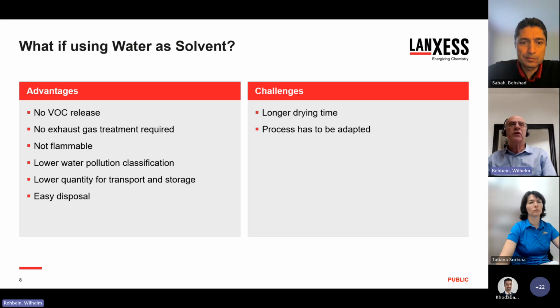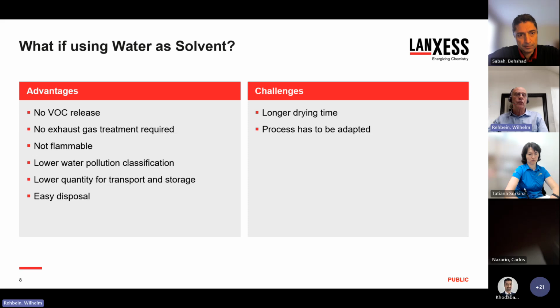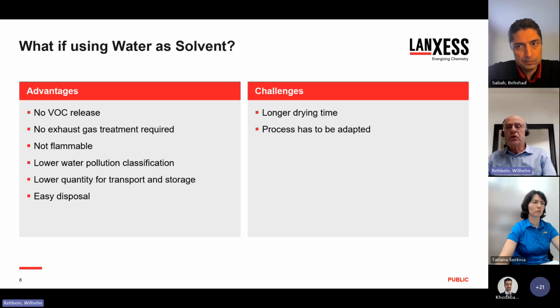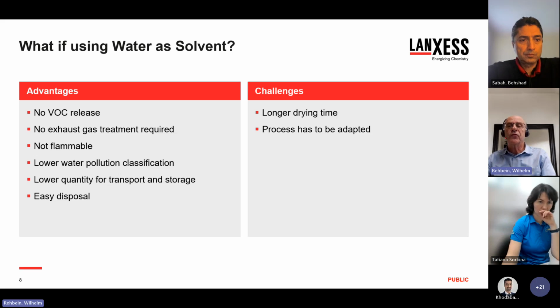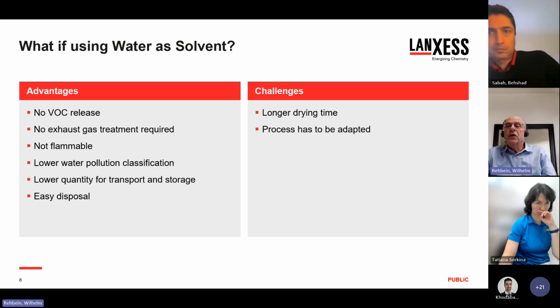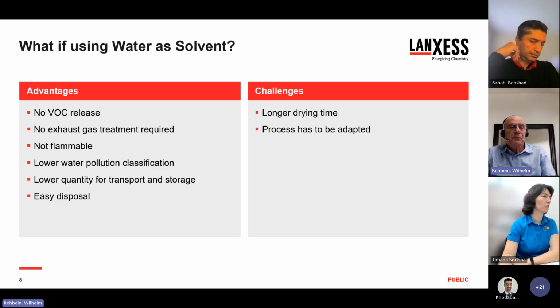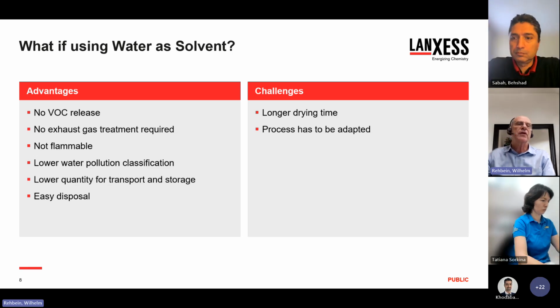But what if we just used water as a solvent? There would be no VOC release because there are simply no volatile organic compounds in the formulation, and therefore there's also no exhaust gas treatment necessary. The rust preventive would be not flammable, and usually it would have a lower water pollution class. The quantity of material that needs to be transported or stored is also lower because 70 to 80% of the finished rust preventive is just water, which is usually available in every manufacturing site. And the disposal is still as easy as for other used lubricants. On the other hand, drying times might be longer, and because it's a new technology, some changes might be necessary in the application process.